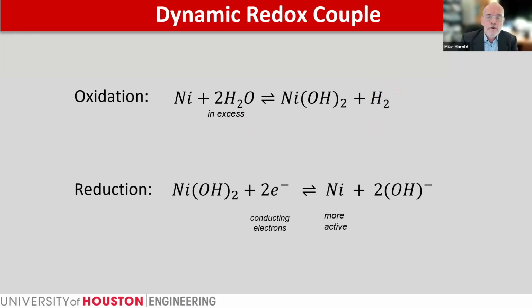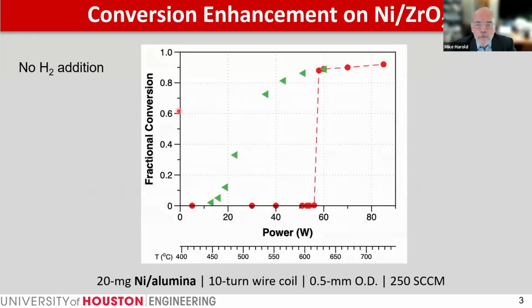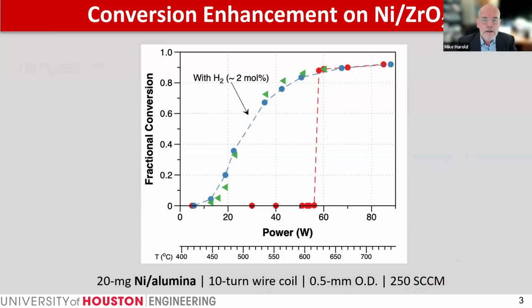Well, one way of testing that is to add hydrogen. So I'm now re-showing data that I've shown you earlier. So this is for a particular 10-turn wire coil. The flow rate here is fixed at 250 cc's per minute. The green triangles are obtained on the nickel zirconia, and these are steady states that we believe exist because of the electroreduction of the nickel oxide and nickel hydroxide. Interestingly, when we add a small amount of hydrogen to the feed, nominally 2%, remembering that the feed methane concentration is 5% and steam is approaching 20%, we get the blue circles. So we basically follow the same trajectory of the conversion that we obtain in the absence of hydrogen.